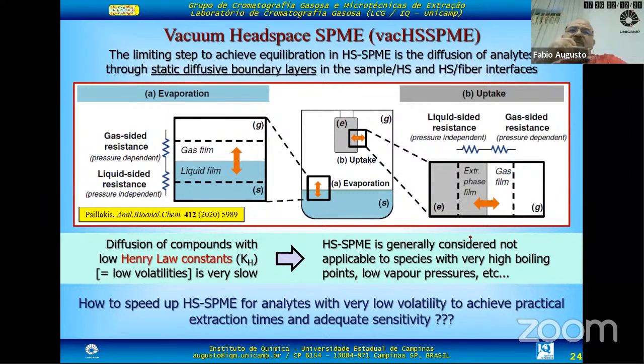Well, the second approach we used was vacuum headspace solid phase microextraction. Solid phase microextraction is sometimes used for headspace extraction. You put your sample in a vial, lock it, expose your fiber to the headspace of that sample, and extract volatile compounds. The problem for extraction of compounds with very, very low volatility, such as those biomarkers, is that you can extract them, but the process would take a very, very long time because the vapor pressure is too low.